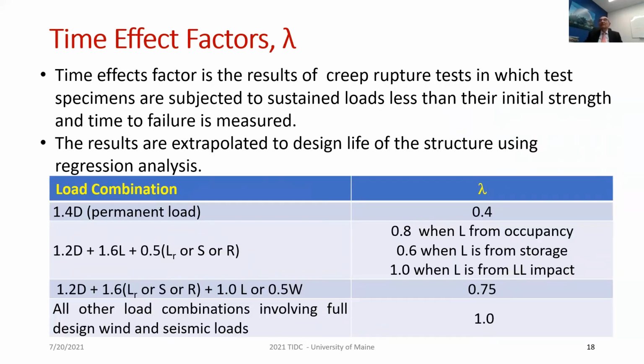Time effect factor is done essentially by subjecting the member, component or structure to a load which is less than its strength and measuring time to failure. Then we extrapolate the results to the design life of the structure. Based on that, we get a knockdown factor on strength. For example, for permanent load using pultruded FRP, you have a factor of 0.4 reduction due to permanent load effect.